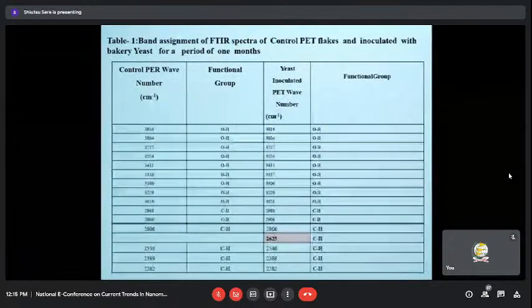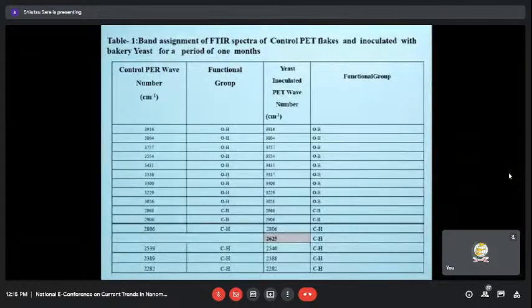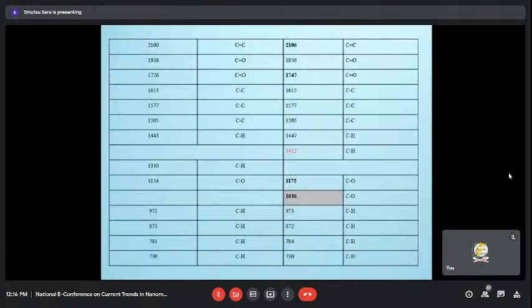This next slide is about the FTIR spectra of the control PET flakes and the other sample that is treated with the bakery yeast. From this table, we can see that new peaks have occurred. The darker shade, at the wave number of 2625, shows new peaks. Similarly, two new peaks have occurred here at the 1412 wave number and also 1036.